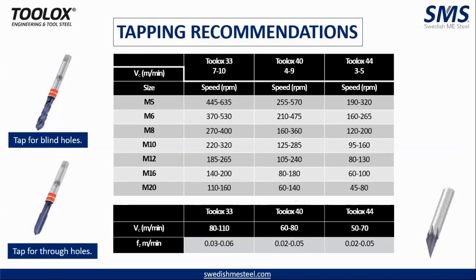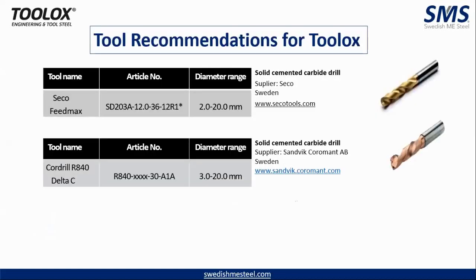For tapping, we recommend machine tapping from M5 to M20. Below M5, we recommend thread milling. We don't recommend tapping below M5. And these are the tool recommendations for drilling. These are all European suppliers. Some of them may or may not be available in India. You need not worry. We have also come up with local solutions for both drilling and tapping. But even then, you can just speak to your current tooling supplier and ask them to supply similar tooling. That should be able to do the job.